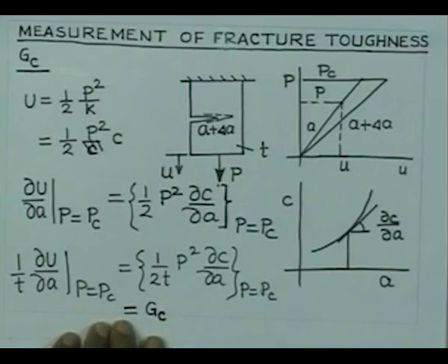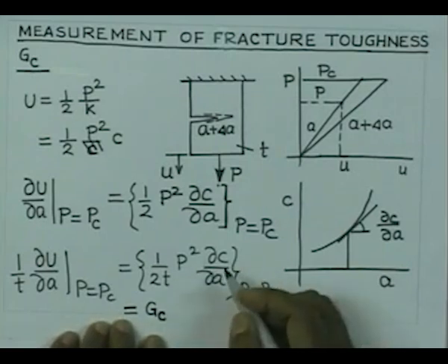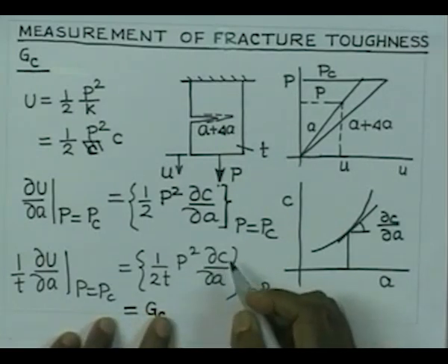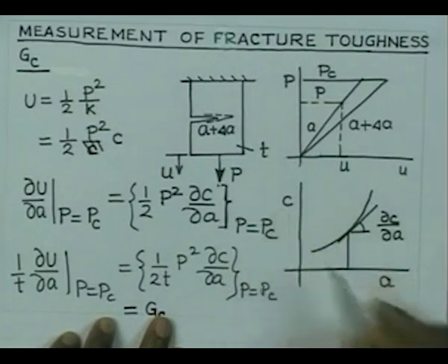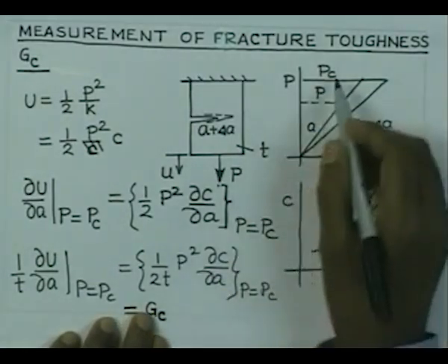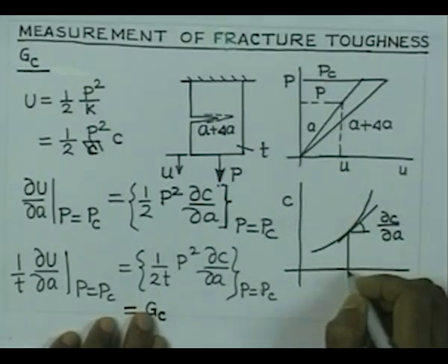Before you can do that, you must have the information available about the variation of compliance of this specimen with crack length, and when you have got this Pc, you take the starting crack length.